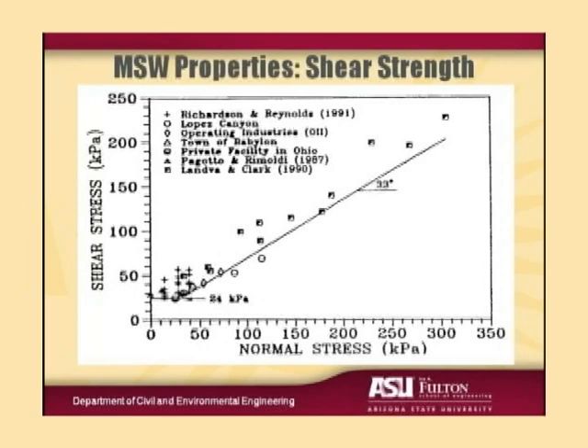At Lopez Canyon, that slope was very close to the epicenter of the Northridge earthquake. It had been subjected to peak ground accelerations on the order of 0.4 to 0.5 G in the earthquake. So we felt 1.1 was a little conservative for that site. Those slopes showed no signs of any long-term deformation or cracking. So we were comfortable having those 2 points below the 33-degree line. And this shear strength envelope is now widely used to represent the shear strength of municipal solid waste. So that was one of the first contributions to practice from this project.